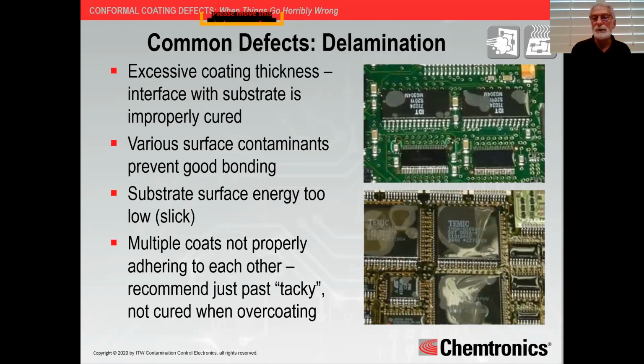Sometimes they just flake. You can see up at the top, in that top picture, you can see areas where that coating is just kind of flaked off. In the bottom, they're flaking, but it looks like almost the entire coating has pulled up from the substrate. Now, if you're doing multiple coats, and I'll throw this out there, we always recommend, if you're doing multiple coating, use thin coats, not heavy wet coats. Multiple thin coats is a much better adhesion practice than heavier coats. They just don't tend to meld together.